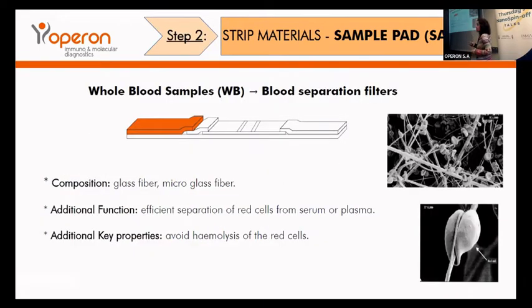When we are working with whole blood samples, it is necessary to use a special sample pad material, which is a blood separation filter, mainly composed of glass fiber. It has an additional function, which is to get an efficient separation of the red cells from the serum and the plasma, because we really don't want the red cells coming into the membrane. This separation must be done avoiding hemolysis of the red cells. Otherwise, the hemoglobin comes into the membrane and dyes the membrane.